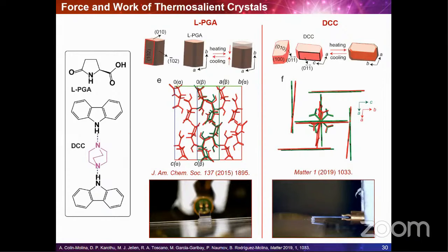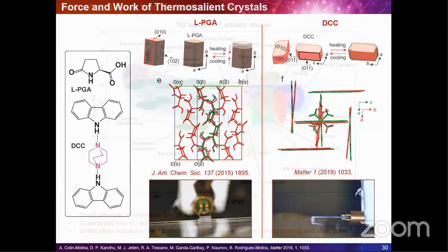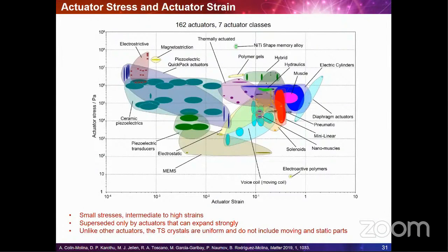And then by comparing these values with an extensive database of actuation, we attempted to identify the relevant parameters and to systematically compare the performance of these two solids with other common actuator classes. For example, we found that they are the lightest of the available thermal actuators, and they currently are also the only lightweight actuators with a single component of uniform composition and ordered long-range structure. However, due to their small size, which is inevitable due to limitations with crystallization, they generate smaller maximum forces than most of the known actuators.